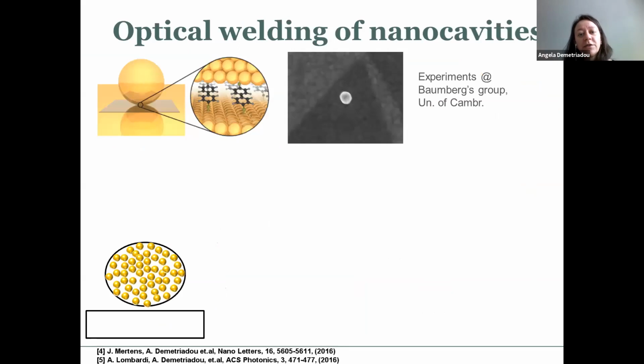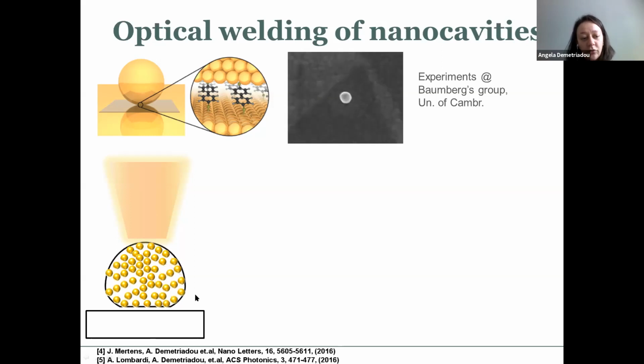Quickly, I would like to say that spherical nanoparticles in reality are not really spherical, they are very rough structures. They have different crystal facets. This is a collection of SEM pictures of the same nanoparticle, and you see that it is basically a polygon. And what experimentalists can do is shine a laser that mobilizes the gold atoms, and you can even control the size of the polygon facet that is opposite to the mirror here.